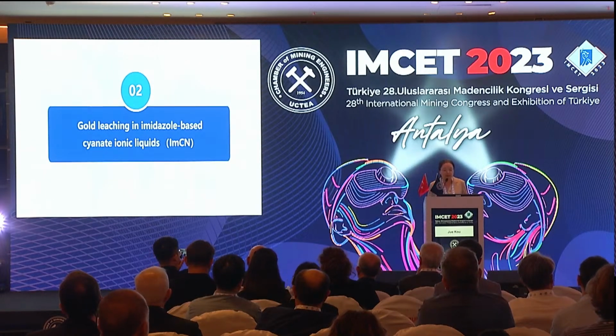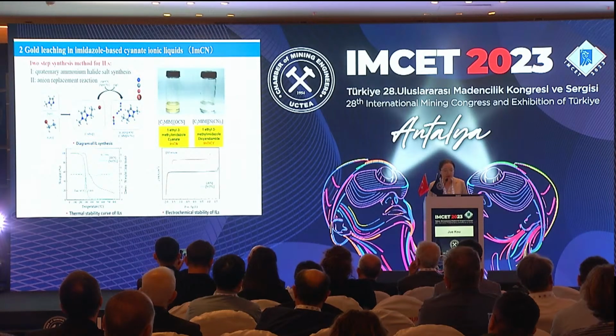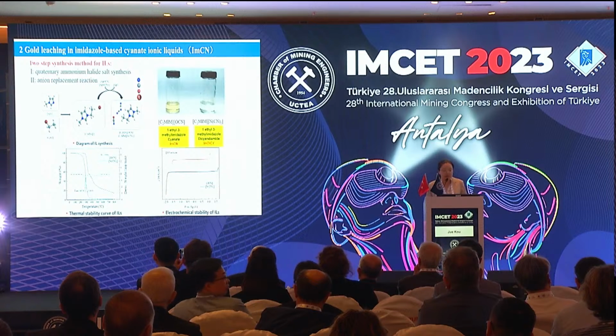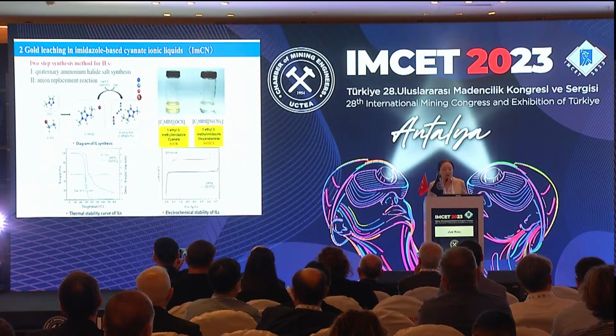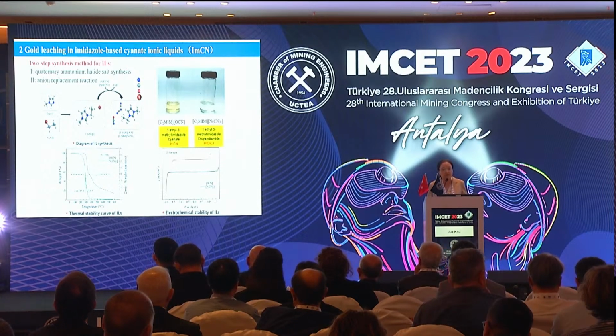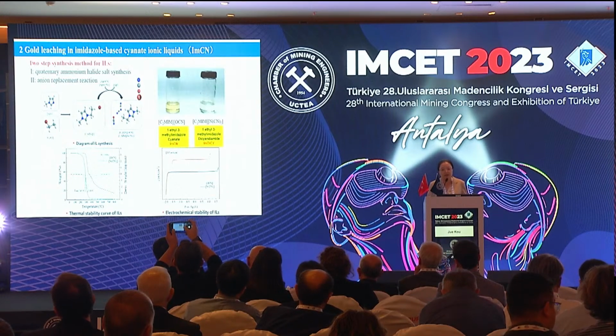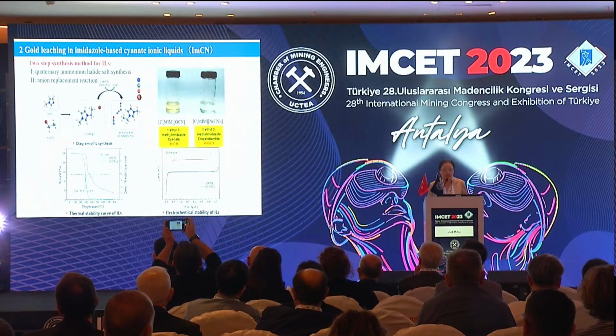Now let's take a look at part 2, the gold leaching in imidazole-based cyanate ionic liquid, ImCN. First of all, I'd like to introduce the synthesis method of ionic liquids. There are 2 steps. The first step is quaternization, to synthesize a quaternary ammonium halide. It's a kind of salt. And with the help of the salt, the middle product, we can do an anion replacement reaction to get the ionic liquids with the certain cation and anions we need in our tests.